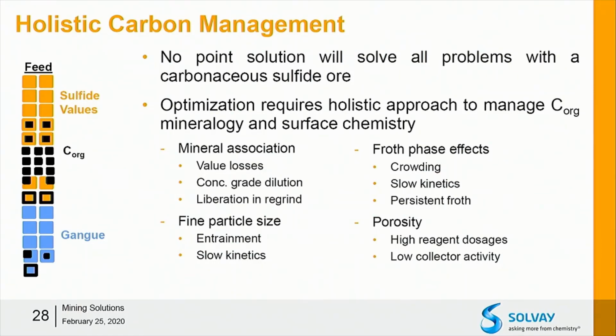Yeah, I think it depends on the nature of what's there, how much is present, and what its associations are. I think there are real benefits to pre-flotation as long as there aren't too many value losses. Or if there are value losses, if there's no alternative in terms of, say, a roasting strategy to actually separate the two. But I think what we see is that because of the reality of liberation of carbon downstream, say in regrind processes, a pre-flotation alone is rarely going to be sufficient, and frequently just because of carbon flotation kinetics, driving carbon recovery in a pre-float is going to lead to substantial value losses.